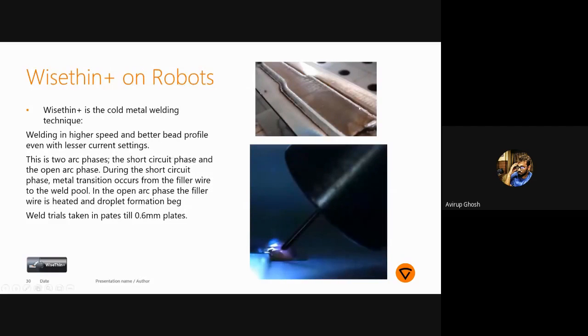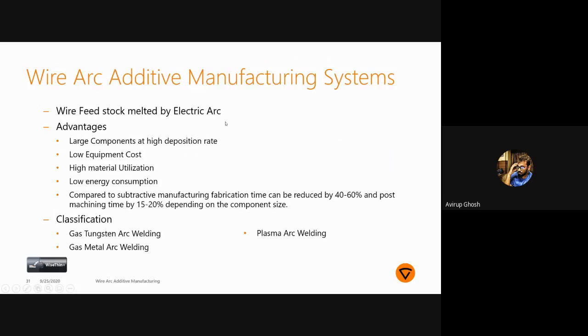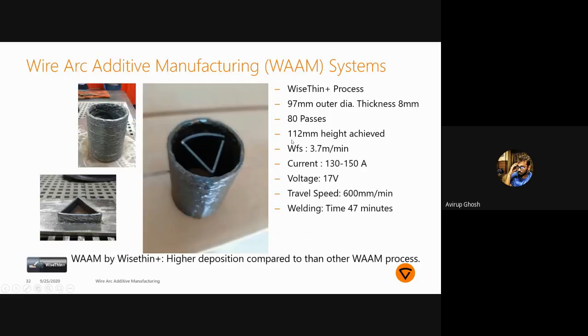An interesting example of this process is a very interesting application happening right now in the robotic field, wire arc additive manufacturing, where we build different kinds of blocks using wire, using metal deposition. Blocks like this can be built up using this process. This is one of the fastest processes for building these blocks. We are building blocks of around 80 passes with a height of around 112 mm in around 47 minutes. So this is one of the fastest processes for wire arc additive manufacturing.